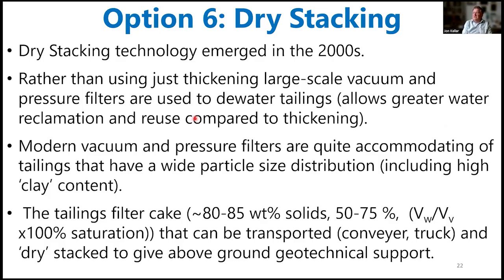Now, in the 2000s, there was a new technology brought on called dry stacking technology. And you can see there are very subtle differences here between the dry stacking and the paste backfill. But what really enabled the dry stacking was large-scale vacuum and pressure filters on the dewatered tailings, where you could reclaim a lot more of the water compared to thickening. They're quite accommodating, even of very fine clay particles, and they'll produce a filter cake that might be 80 to 85 weight percent solids. And you'll start seeing this term percent saturation, basically how compressed these bricks or filter cake are.